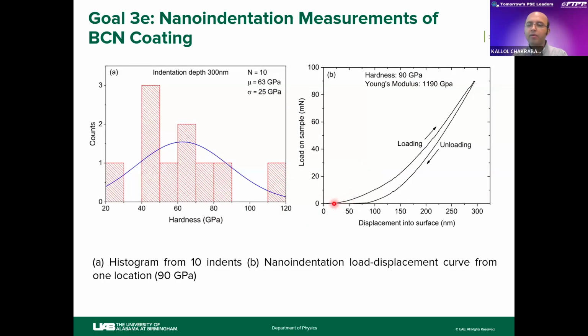When we measured the load displacement curve, as the indenter was indenting the surface, this is the loading curve and this is the unloading curve. From the loading and unloading curve, we can definitely say that most of our deformation is elastic deformation, and only 20% is plastic deformation. That also confirms our sample is a superhard material.